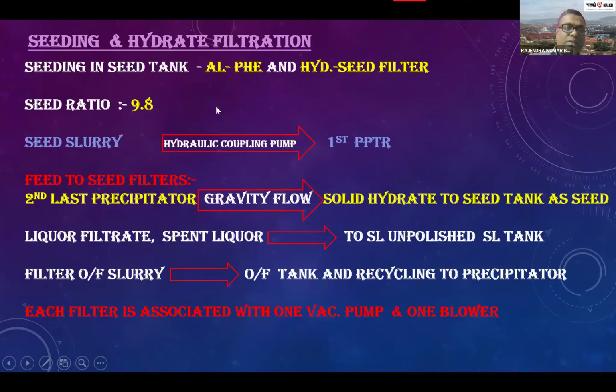Seeding in the seed tank. Aluminate liquor and hydrate seed filter. Seed ratio is 9.8. Seed slurry for seeding. Hydraulic coupling pump, first precipitation. Feed to seed filter. Second last precipitation, gravity flow, solid hydrate to seed tank as seed. Liquor filtrate and spent liquor go to the spent liquor tank. Filter overflow slurry goes to the overflow tank and is recycled to the precipitator. Each filter is associated with one vacuum pump and one blower.